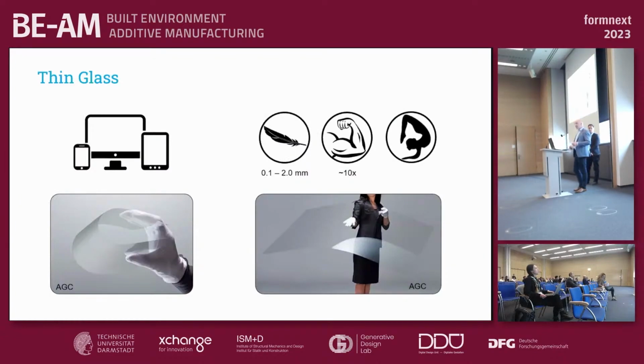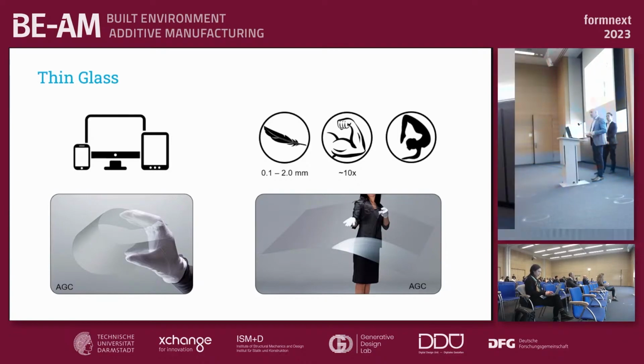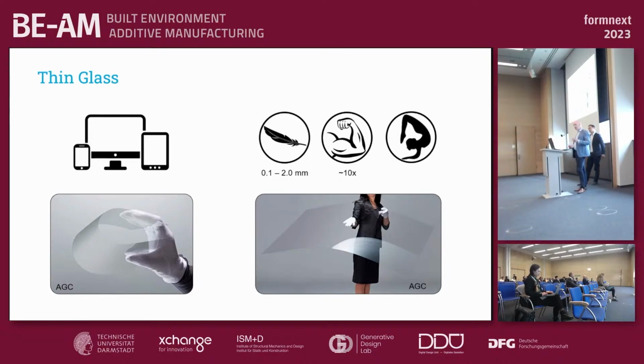It started all with thinking about how you can use thin glass, and then I refer to the glass that you have on your devices, your mobile phone or your tablet, which is in the range of 0.1 to 2 millimeters, let's say. And it's very strong because it has been chemically strengthened, so 10 times stronger than regular glass, more or less. And it's also very flexible, so you can easily flex the glass in desired curvatures. So this is a piece of thin glass, and you can see that you can easily bend it into desired curvatures, so by hand, by cold bending, we call that. Many people think it's plastic, but it's really glass, actually.